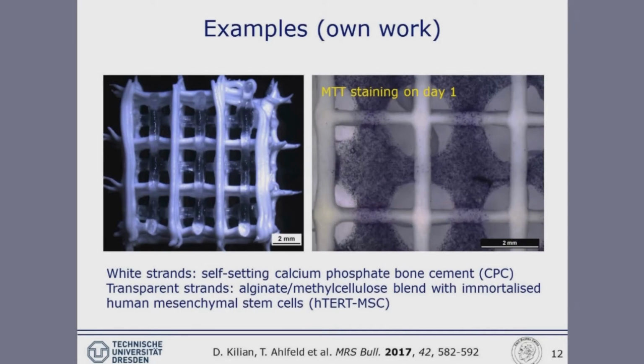What does the structure look like one day after printing? As I've mentioned, the cement is a self-setting material, mostly based on the chemical reaction from alpha-tricalcium phosphate towards hydroxyapatite, the calcium phosphate phase of human bone. This is the stiff, supportive part of our combined scaffold. And here the little bluish dots, these are healthy and active human mesenchymal stem cells. We used an immortalized cell line, hTERT MSC, and we stained this with the MTT stain, which is only transformed by really active and healthy cells to this dark violet formazan derivative. So a nice proof that we have living cells inside.